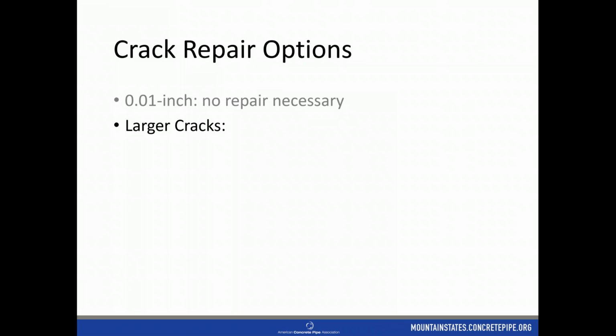Now, if you have some larger cracks, let's say you have a crack that goes all the way through the pipe, and you're worried that it's going to be leaking, this is a situation where maybe autogenous healing isn't going to work. I've seen somewhere you've got a weep hole and water spraying through, right? You've got a gusher, because there's maybe some high groundwater outside pushing against it. That gusher's never going to get a chance for those calcium carbonate crystals to form to seal that hole. If you've got a big crack and it's gushing through, it's never going to slow down.